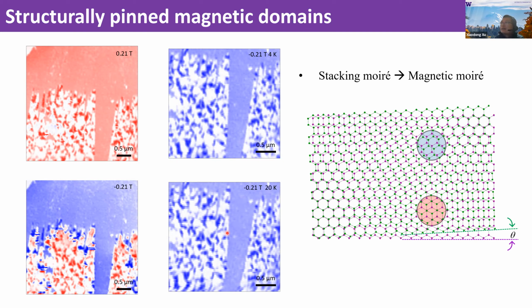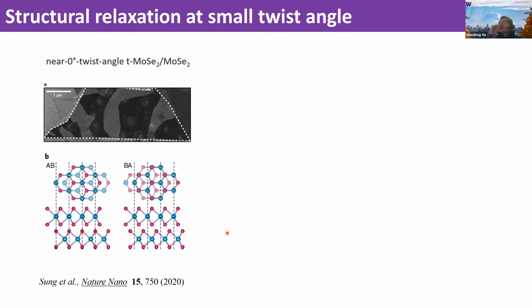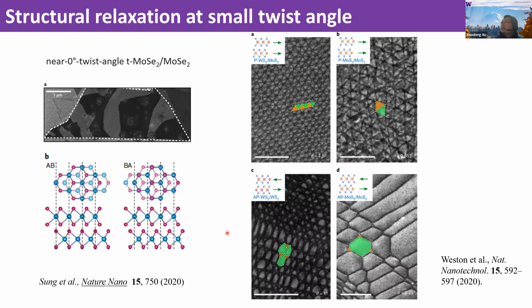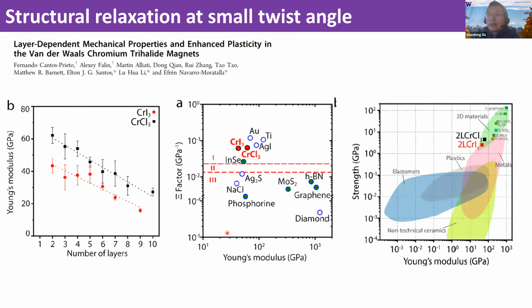So now the question is why we don't observe these Moiré effects, but we see these disorder effects. The reason is that we know for these small twist angle samples in TMDs or graphene, people already showed there are lattice reconstruction effects and it doesn't look like a Moiré. It's just a couple examples. I'm gonna skip this due to the interest of time. But I would like to mention that chromium triiodide is actually a really soft material compared to TMDs or graphene. For example, the Young's modulus of graphene is on the order of terapascal, but the Young's modulus for these 2D magnets is on the order of 30 gigapascal. So it's about 30 times weaker.